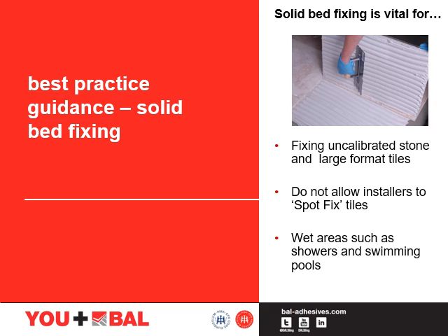Depending on the size of the tile, as formats get larger, the stone might require back buttering. Spot fixing should never be used when tiling, as this will lead to cracking and reduces the bond strength by reducing the percentage of adhesive touching the tile. For floors, a hidden void could lead to tiles cracking under loading, and for walls, insufficient adhesive contact could reduce capacity to carry the weight of the tiles and cause them to slip or fall. It's advisable to make sure that your specification calls for 100% solid bed fixing, especially in wet areas. When fixing, varying sizes may require varying bed depths — consider using a thick bed pourable type adhesive.